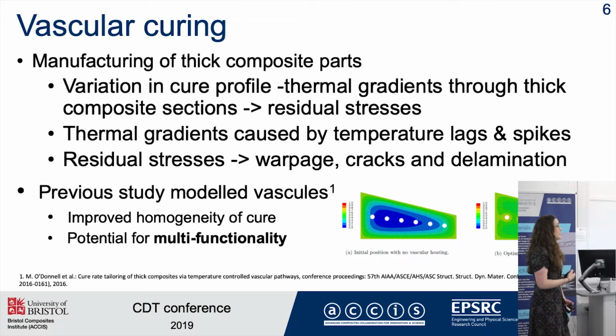So then vascular curing. We're looking at the manufacturing of thick composite parts. If you've got a thick composite, you end up with issues from variation in cure profile, with thermal gradients through thickness, resulting in temperature lags and spikes, which would lead to residual stresses which create manufacturing defects such as warpage and cracks and delamination.